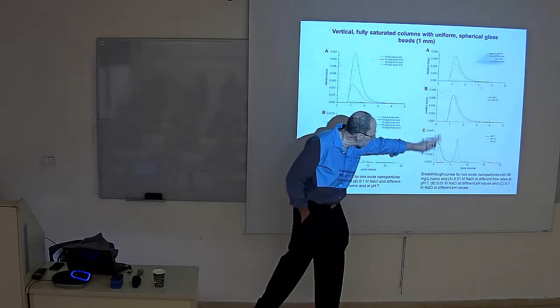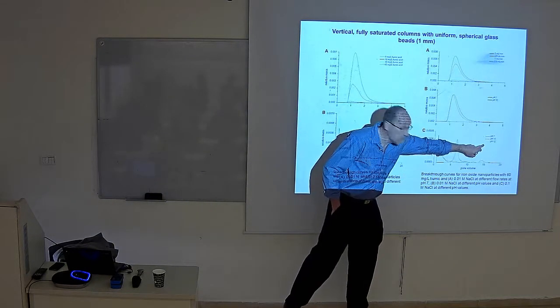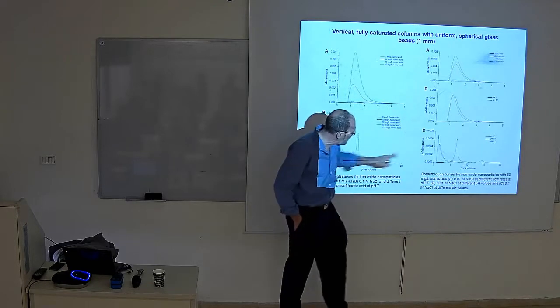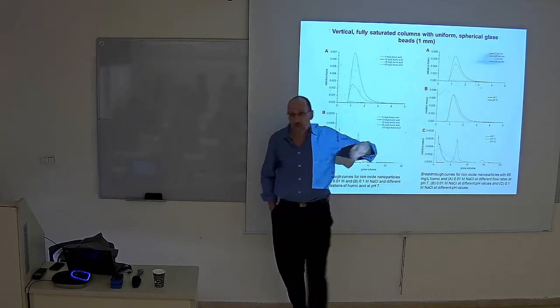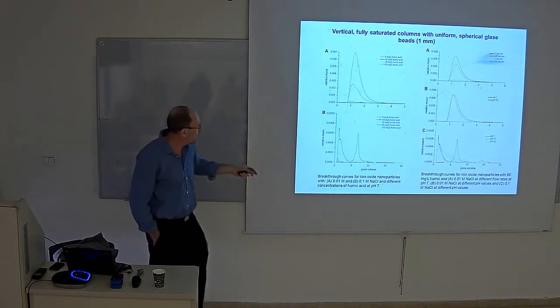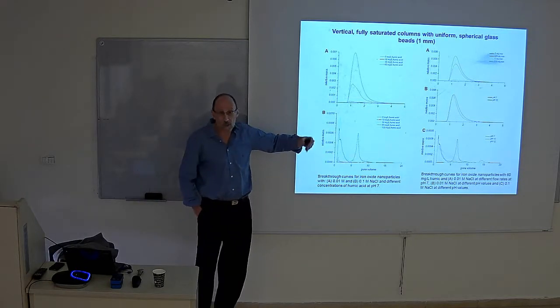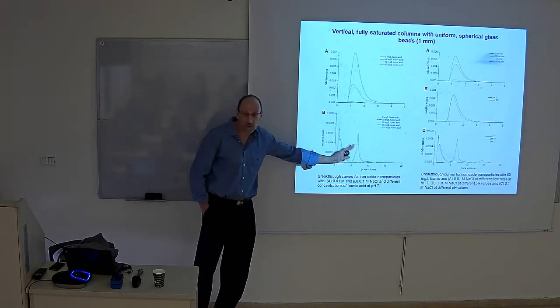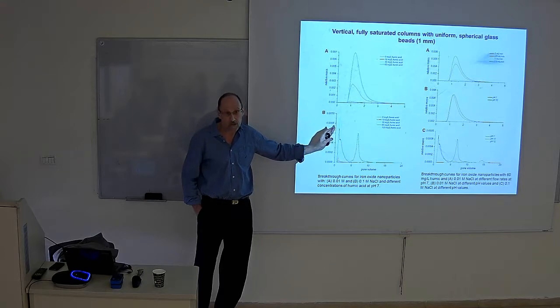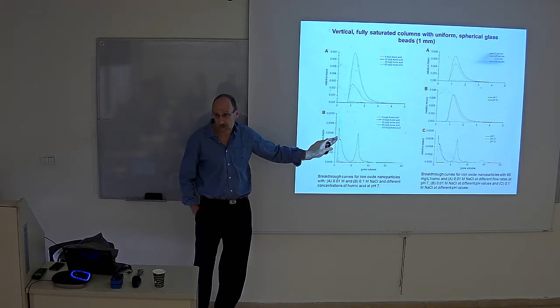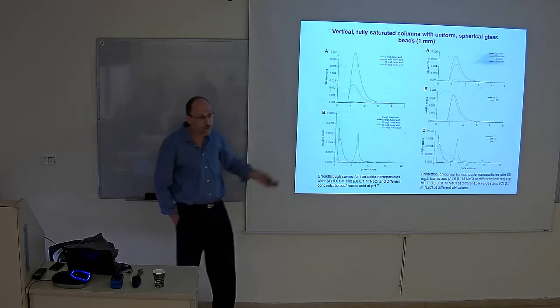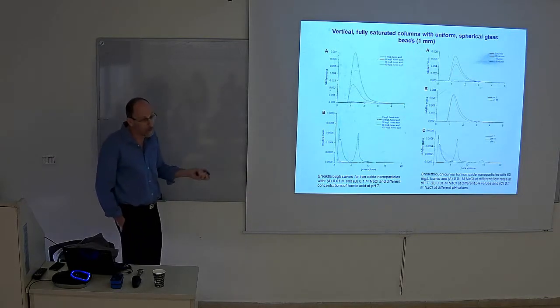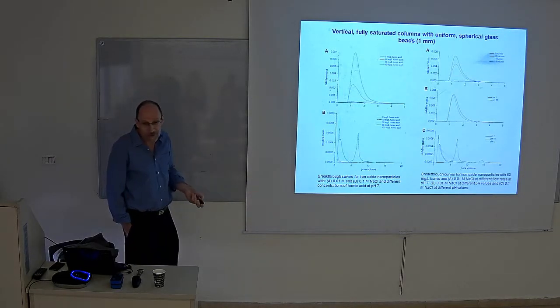We did a whole bunch of different experiments. Here, this is effective pH, by the way. Okay, so that's the salinity, that's the effective pH, and you get these pulses coming through. Do the experiment several times, and each time you get pulses appearing, but of course they're not consistent in terms of the when and the quantity because of the randomness. So you can understand the phenomenon, but to try and model that, it's not for me anyway.